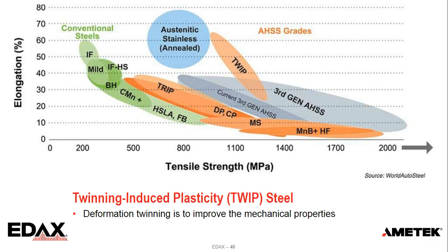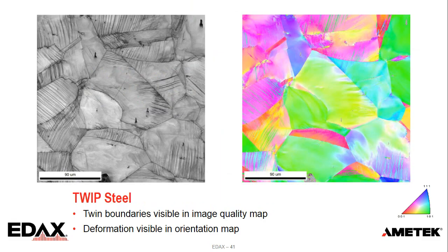So this is just a little diagram from World Auto Steel. And for TWIP steels, deformation twinning, and being able to measure and understand that, is what's used to achieve these superior mechanical properties. So this is, again, an image quality map of a TWIP steel. You can see the twins come out as those parallel linear features within the microstructure.